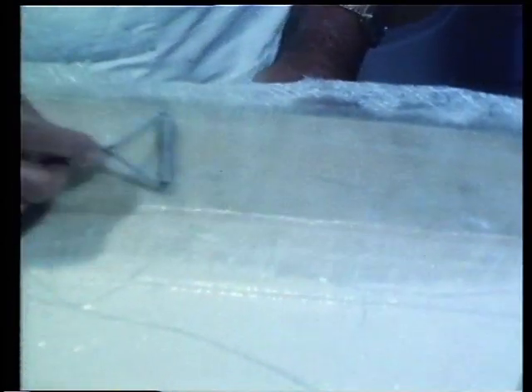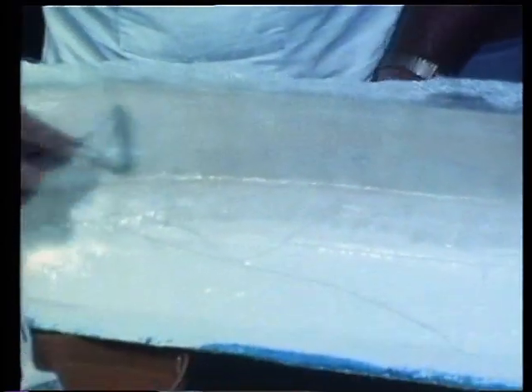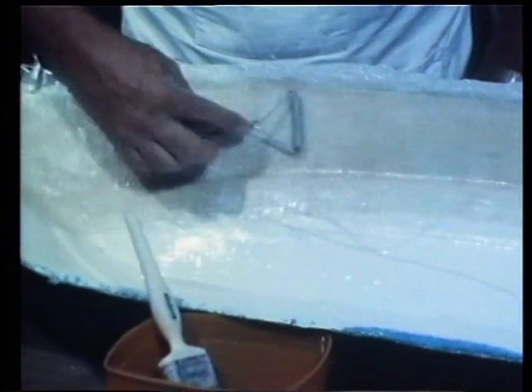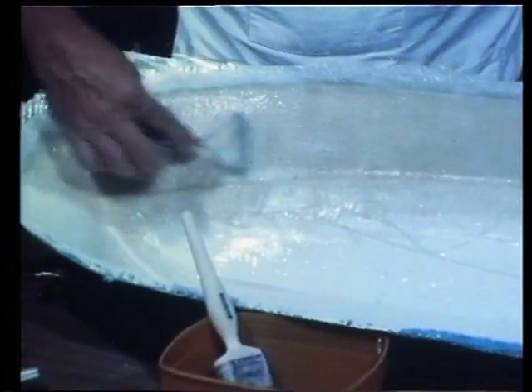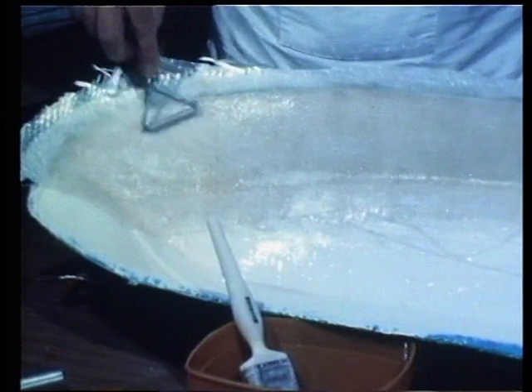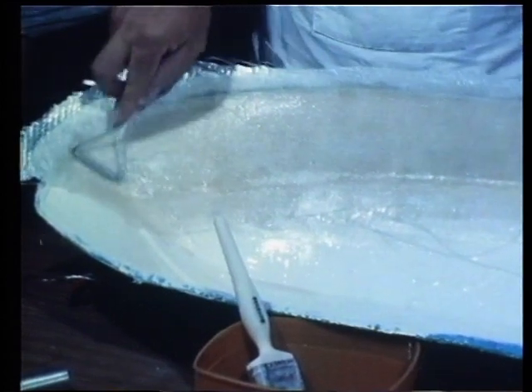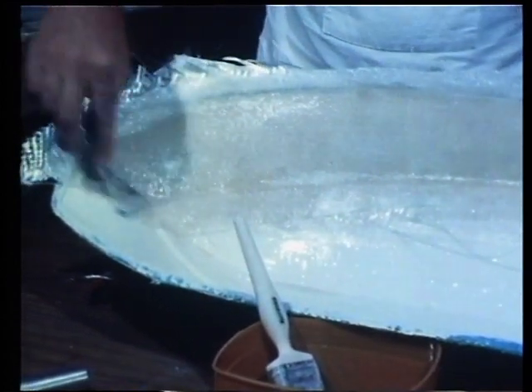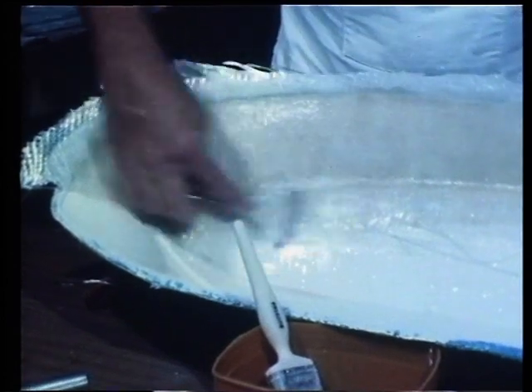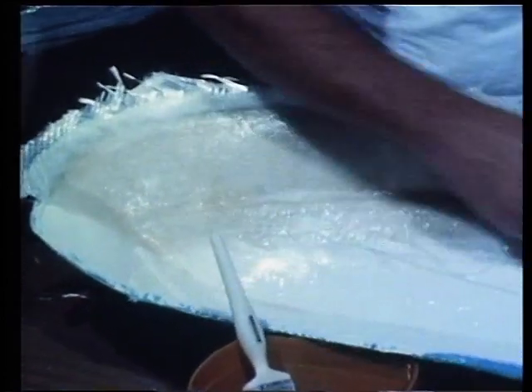And as I go over it with that roller, you can see the way in which the resin's being squeezed up into the mat and the mat is being completely wet out. Now, it takes a minute or so for the white colour to disappear because of the length of time that it takes for the binder to be dissolved by the styrene in the resin. But fundamentally, that is the way you do it.